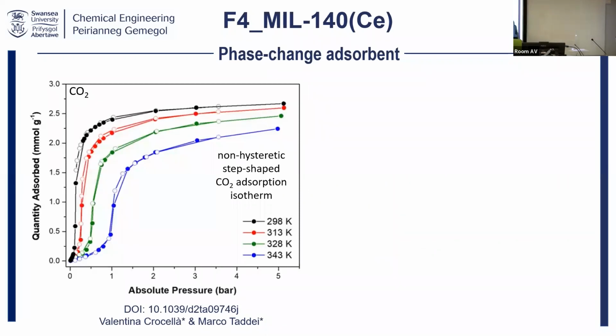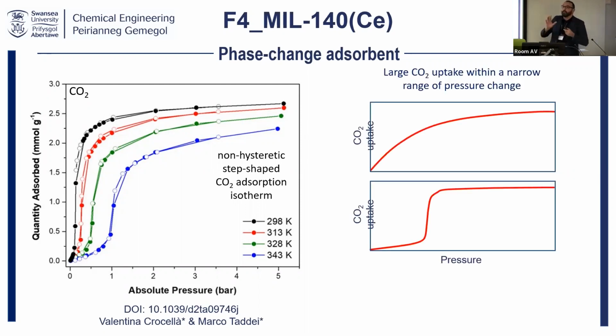allows us to obtain an adsorption curve of this kind, which has a step change in the middle. It's called a step change curve of absorption. So again, pressure of CO2 and how much CO2 gets stuck on the surface of the material. So why does this all make sense? And why would this material be a promising one for pressure swing adsorption? With solvent amines, when you want to recover CO2 absorbed inside the solvent, you need to swing the temperature. Instead, on this material, when you want to recover, so peel off the CO2 from the material, you need to swing the pressure.